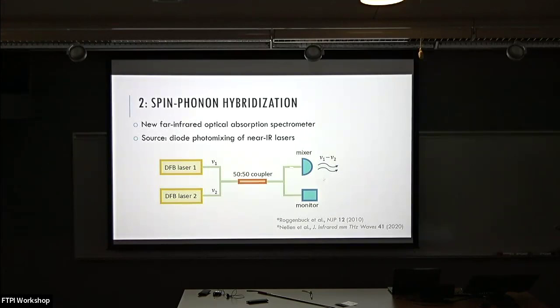So this is a special diode. You shine 2 lasers on it, and it gives you the difference between their frequencies. So if you have two lasers, you can control their temperatures. Through that, you control the wavelengths. You mix them with the mixer, and you get out a continuous wave sub-terahertz radiation. And this is sweepable in a very wide range. So right now, the system can do something like 50 to 800 gigahertz. So it's right where we want it. And it's also quite useful for a bunch of other things.